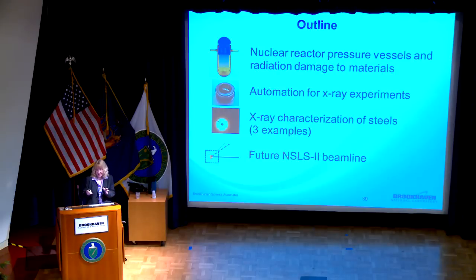You bring up a very good point, right? That's almost like another variable. So the reactor pressure vessel is enormous, right? Most of the radiation damage is going to occur in the beltline region of the vessel. So that's the region adjacent to the core where the neutrons are coming out. And then in addition to that, the vessel can be 20 centimeters thick. So the material closest to the core is going to experience more damage than the material farther away. So that's another set of variables. So you have to understand the performance of the material throughout the entire structure, and you need to incorporate that into your engineering scale models.